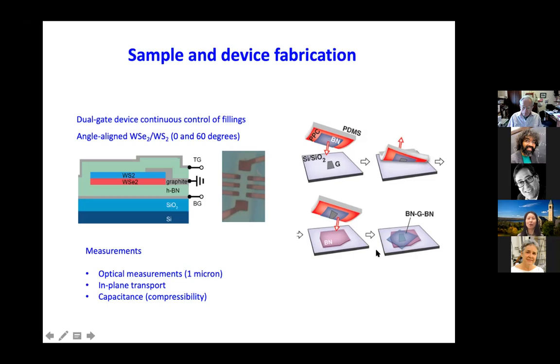Then you just raise the temperature of your polymer. The whole thing will be deposited on your substrate, and the polymer can be cleaned out. And this hexagonal boron nitride will protect your sample because your sample is not exposed to anything else. So we can get atomically sharp interfaces and very, very low contamination. Then we can do further lithography. You can put on contacts, you can etch them, and make it into a Hall bar, whatever. So that's how we make those samples.